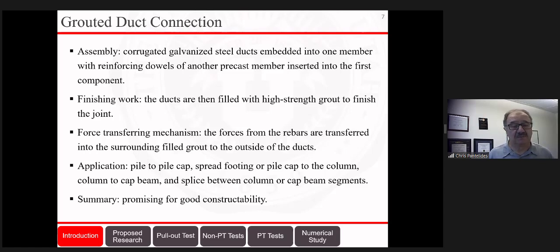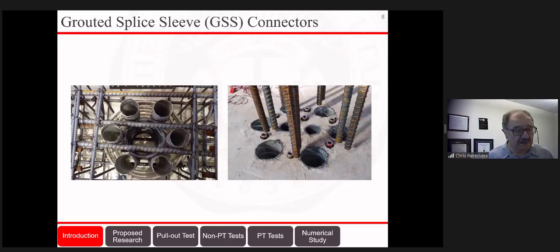It can be used, for example, pile to pile cap, spread footing or pile cap to column, column to cap beam, and splice between column or cap beam segments. So this is a promising connection with good constructability, and that's why we used it ourselves. Here you can see how the columns were typically constructed. They're constructed with 6 grouted ducts, 2 inches in diameter. In this case, we're using an all-steel column, but as I mentioned earlier, we also used a hybrid, which means some of the bars were steel and some of the bars were fiberglass.